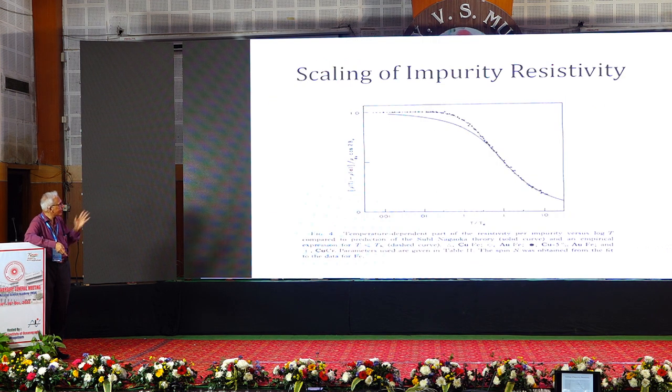And here I show you some experimental data, which is like a triumphant verification of this. There are many, many materials here, different impurities, combinations of different magnetic impurities in different host metals. And all of them you can collapse. If you were to scale each of the data by 1 over the appropriate Kondo temperature, you can collapse all of them into one universal curve, which is experimentally known, but you're still not able to calculate it theoretically and show that it should be that curve. And that's the problem that Wilson was able to solve.